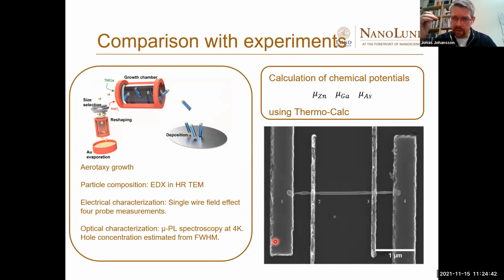So if we compare with experiments now, I remind you that we have grown our gallium arsenide nanowires in aerotaxy and in the presence of diethyl zinc as a dopant. So we measure the particle composition post-growth by EDX in a high-resolution TEM. We measure the doping using electrical characterization by 4 probe measurements with this kind of setup. So the nanowire is here, and here we have the 4 measuring points. And we also optically characterize doping by broadening of the photoluminescence peak.